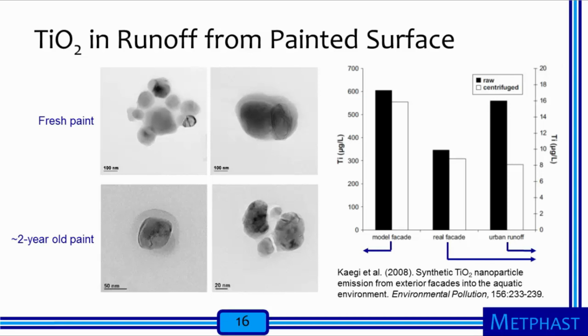The total raw concentration of titanium in the runoff from the freshly painted surface was about 600 micrograms per liter. When the runoff sample was centrifuged to eliminate particles larger than about 300 nanometers, the remaining concentration was about 550 micrograms per liter, indicating that the overwhelming majority of the titanium mass in the runoff was associated with particles in the nanoscale or near nanoscale range.